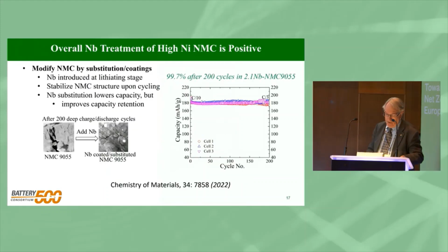So what is it really doing? We introduced the niobium at the lithiating stage. We found that it lowers the capacity, but what it is really doing is preventing those meatballs from cracking. Here's a typical niobium-free material. You get these large cracks after 200 cycles. Add the niobium, and you get some minor cracks between the particles, but none of these large cracks. These large cracks allow electrolyte penetration, which then forms resistive films on the surface, causing that increase in resistance and loss of capacity.